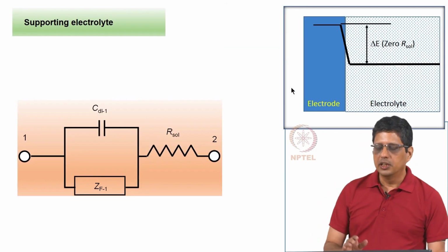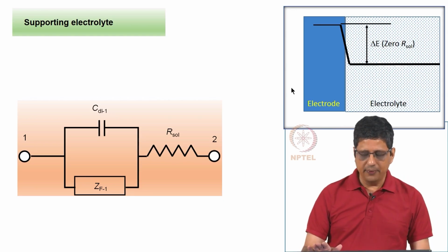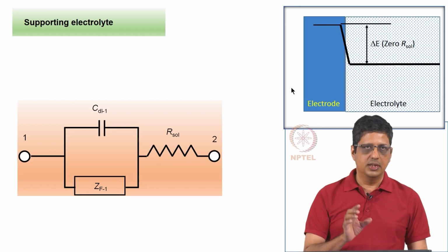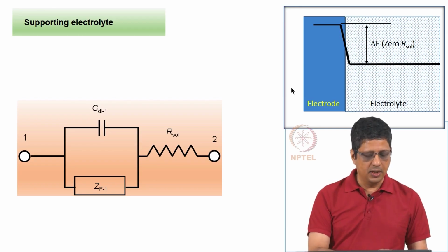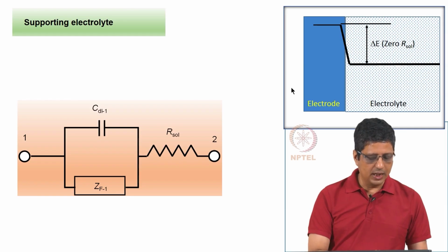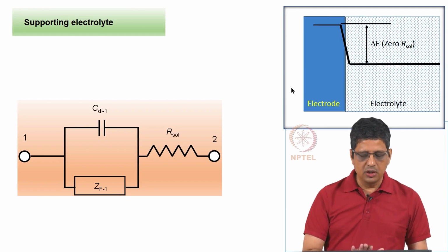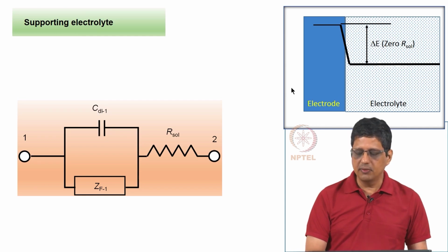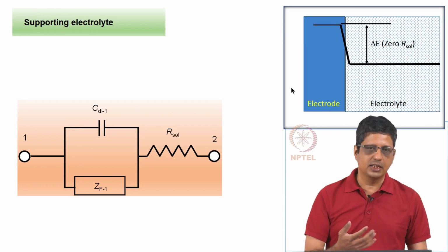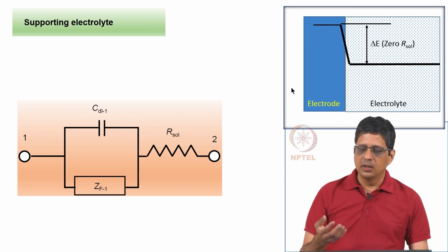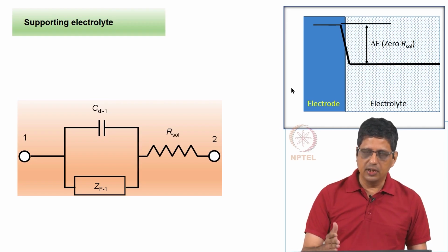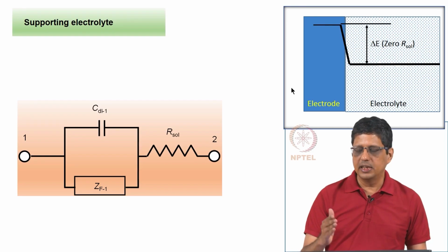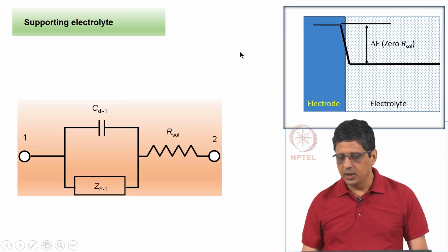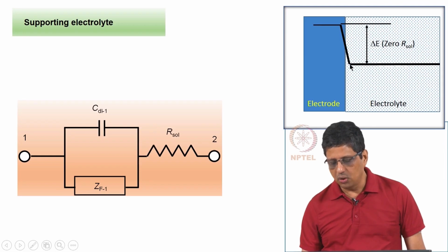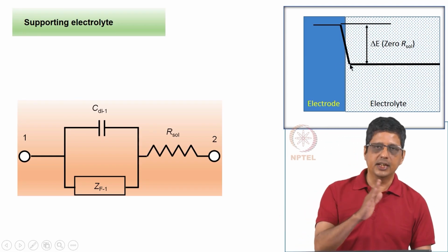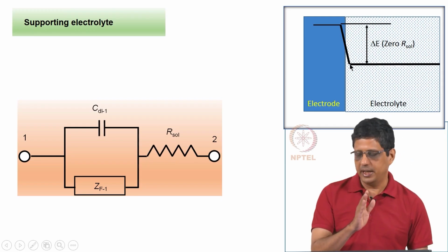Okay. If you have good conductivity, if you have a lot of supporting electrolyte, then you can take this model. This is for a good reference electrode. The model in orange color is given for a good reference electrode, the working electrode is given as CDL and ZF. Solution resistance is present. If it is negligible, when you have a lot of supporting electrolyte, for example sodium perchlorate, then all the potential drop in the working electrode will occur just across the interface. If you look at the potential I have drawn here, it is going to go from a large voltage to a lower voltage in a very small space. This is to indicate about 1 nanometer or so across the Helmholtz plane.